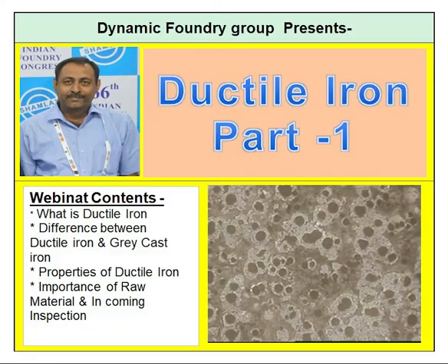Charge sequence, CRCA, you can use GPC or carburizer, but GPC gives a better result. Carburizer has higher melting point, it takes more time to get dissolved, so there are chances that your carburizer will not give 100% recovery when you take the sample. And then you will not get consistent results. So it is better to use GPC, though it is a little bit costly, it will give you better results in terms of quality, recovery, and you can avoid late additions as well.